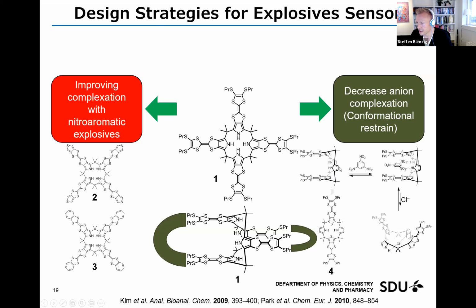But not having the TTF units on the opposite side with the pyrrole actually makes it a much less of a hydrogen bond donor, and this was reflected in the binding constant between TNB and this calix[4]pyrrole, which only had a Ka of 4, and it didn't really bind anions. So this type of experiment actually resulted in a more favorable binding of explosives, but with a much less affinity overall. So it could not be applied within sensing explosives.